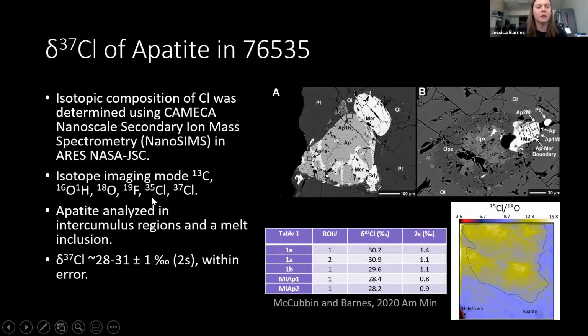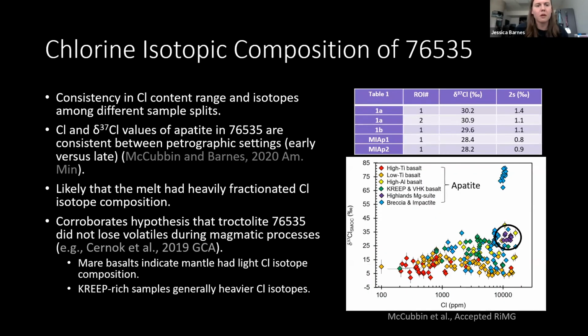For this work, we were looking at the chlorine isotopes. We also measured hydroxyl and fluorine. Oxygen is kind of our internal standard, and then carbon to navigate away from cracks. And what we find, we analyzed both intercumulus and melt inclusion apatite and find them to be almost indistinguishable in their chlorine isotope compositions. So the range that we got was plus 28 to 31 per mil, which are essentially, almost within error. And so we saw consistency in the chlorine isotope range and the chlorine content of the apatites we looked at between different samples that we previously looked at for the intercumulus grains, but then also between the intercumulus and the melt inclusion apatite, so those occurring in different petrographic settings.